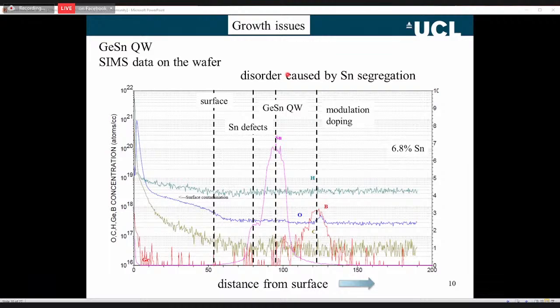They also know from the SIMS measurements that the tin also surface segregates, so we get this second peak here in the tin. Tin likes to stay on the surface as you grow. So they have to use low temperature growth to incorporate the tin. I think the tin is a very large atom.